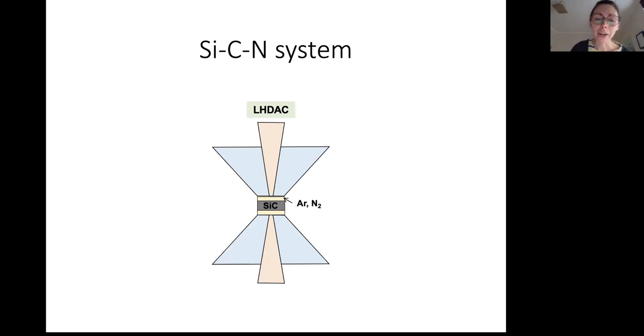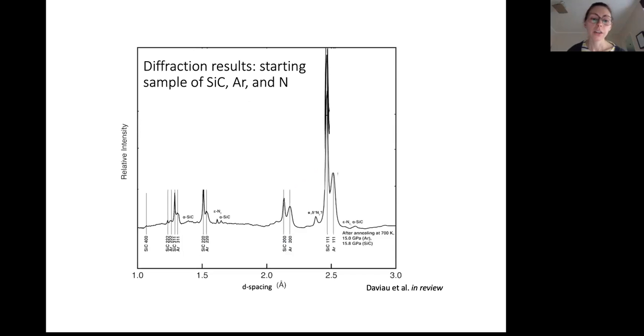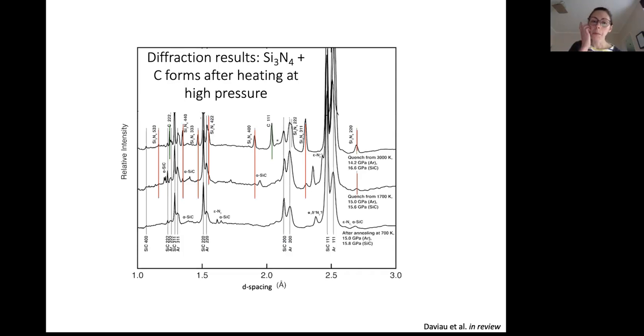But what we have for our sample scenario here is silicon carbide loaded with a mixture of argon and nitrogen, which we then heat up and take to the synchrotron. So the diffraction patterns that we observe from these experiments, looking at silicon carbide and nitrogen: our starting pattern here is argon and silicon carbide, as expected, and then these nitrogen diffraction lines here. These are high pressure forms of nitrogen. So this is at low temperature. And then once we heat it up, these two diffraction patterns are quenched from 1700 Kelvin in the middle, and quenched from 3000 Kelvin up at the top.